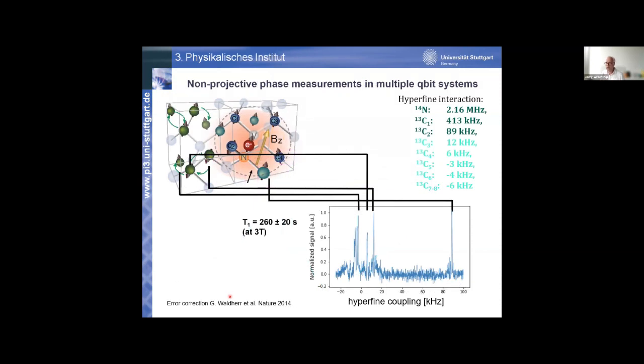One remark to these nuclear spin memories. Up to now, we were only talking about the electron spin doing any measurement. But this electron spin is living in a diamond, and if you do not isotopically purify the diamond, with 1% probability, you find a carbon-13 nuclear spin in the surrounding, right? You can isolate these, or you can measure the hyperfine coupling of this electron spin to these nuclear spins. Typically, they are on the order of a few megahertz down to a few kilohertz, depending on the distance. So mostly it is dipole-dipole interaction.